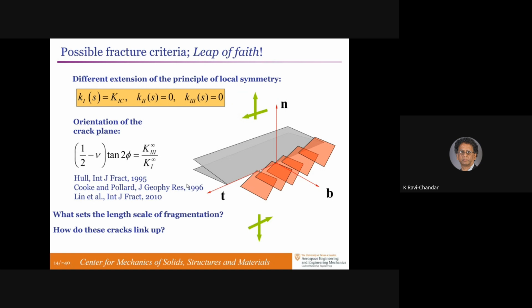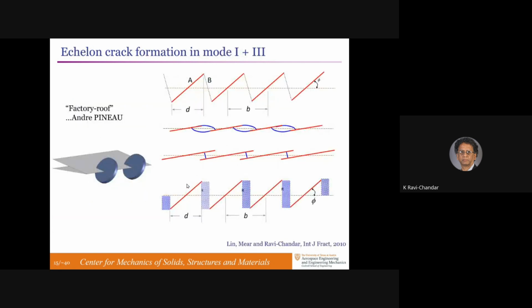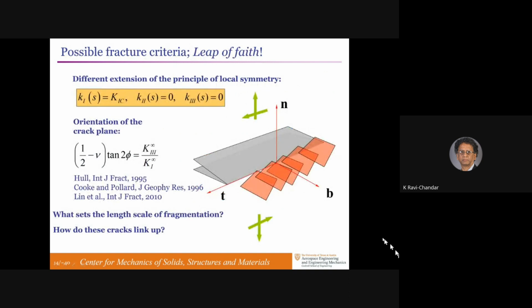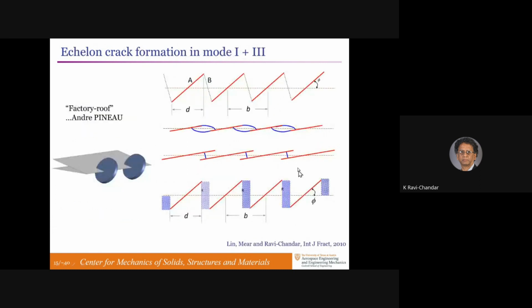So we went back to the experiment to see, can we find what sets the scale of this fragmentation and figure out how these daughter cracks link up eventually to fracture the whole specimen. First, about how the daughter cracks could link up. If you look from the negative B direction at a slice in the NT plane, you'll see these cracks. They're separated from each other, but the ligament between them is not broken. So you just have these cracks popping up that are disconnected from each other and connected only at the back of the parent crack, and there's no continuous path to a fracture surface.